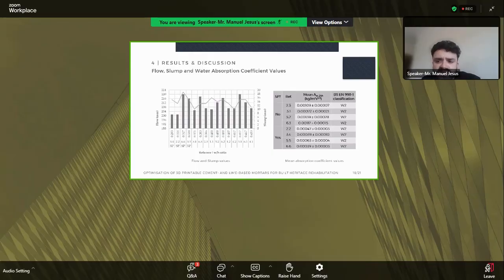As established in the literature, the hydric performance of mortars is closely linked to their porosity, influenced by binder content, aggregate grading, and the water-to-binder ratio. So among the mixtures without superplasticizers, formulation 3.1 demonstrated the lowest water absorption coefficient, and this indicates a denser and less porous matrix attributed to its higher cement content that facilitates a more cohesive and compact structure.